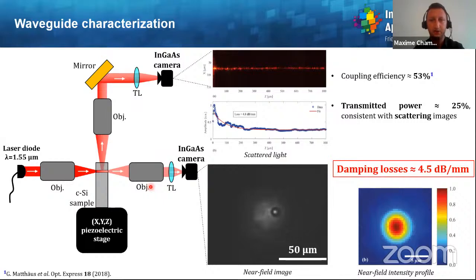First, in transmission, as you can see here, we have an infrared microscope, which enables us to retrieve near-field images. Besides, we have another transverse microscope, which allows us to get some scattered light images. With this, we have measured single mode waveguides with a coupling efficiency of around 53% and a transmitted power of around 25%, which is consistent with scattering images. The near-field images and all the measurements in transmission are quite consistent with the scattering images.